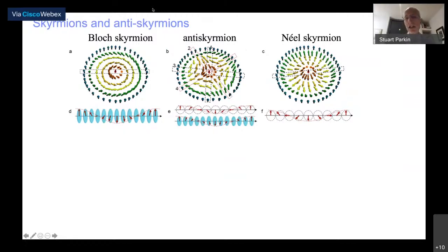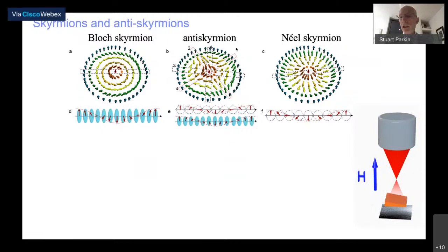Now it turns out there's another object, an anti-skyrmion, which has a much more complex structure. So the boundary, as you can see, hopefully in the middle of this foil, the boundary has alternating Néel and Bloch components to the wall. So as you go around the circumference of this object, then the wall changes from a Néel wall to a Bloch wall, backwards and forwards, and the chirality is also changing. This leads to very interesting transport properties. But we were the first to discover this anti-skyrmion just 3 years ago. And how did we do that? We did it using Lorentz transmission electron microscopy. You basically transmit a very high energy beam of electrons, in our case 300,000 volts, through a very, very thin lamella, which we cut out of a single crystal using focused ion beam milling.